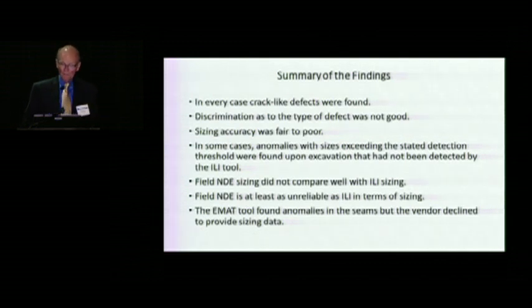Quick summary of the findings. In every case, the tools found crack-like defects. There was no question the tools could find defects. The discrimination as to the type of the defect was not good. And by that I mean, most tools will give you things like crack-like, notch-like, and so on. But what's really needed in ERW pipe is: is it a hook crack? Is it in the bond line? And the tools, at this point in time, were not capable of doing that. The sizing accuracy was fair to poor, and in some cases the anomalies, we found sizes upon excavation that were not stated to be detected in the list of anomalies, but were larger than the threshold size.